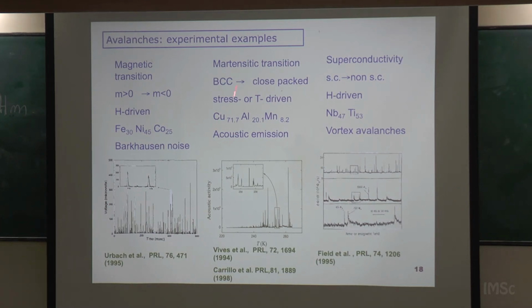This is the case where we participated: martensitic transitions in solids, in this case copper-based alloys. And the technique in this case is also very sensitive to changes in the strain. When there is a small deformation in the system, we can detect it. This technique is acoustic emission, which I will explain to you now. But acoustic emission is almost exactly parallel to Barkhausen noise. Barkhausen is for magnetic systems; this is for elastic systems, let's say ferroelastic systems, if you want.